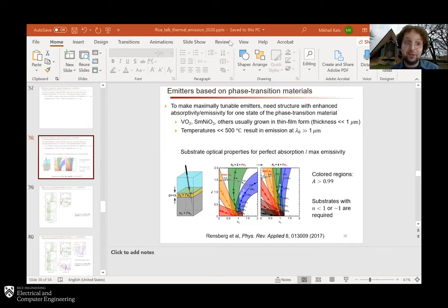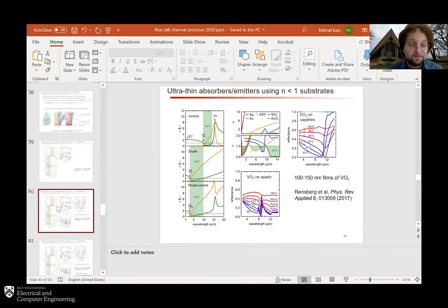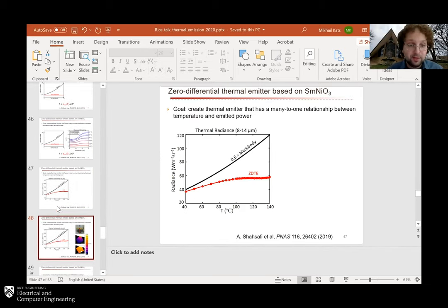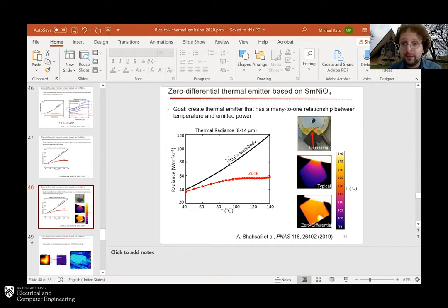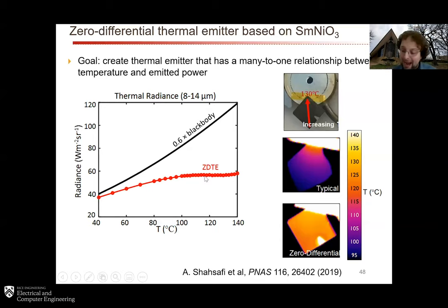This is a little bit counterintuitive. It kind of feels like you might be violating some sort of thermodynamic considerations, but it's actually not, because of what we're doing in all of our measurements. So, for example, let me go to this measurement. We're doing measurements not at constant power being pumped into the sample, but at constant temperature. So we set our heat stage to, let's say, a temperature of 120 degrees, and we do a measurement. Then we change the temperature to 80 degrees, and we do a measurement.